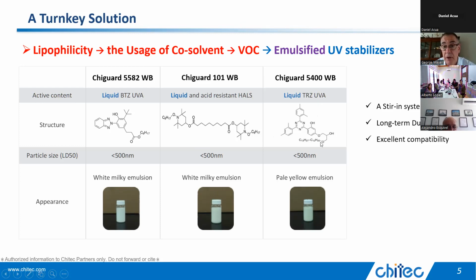The other UV absorber is a triazine. It's ChiGuard 5400. It's really the same molecule as our ChiGuard 5400 without the WB, just emulsified in a concentrate. The same molecule that Ciba-Geigy used to sell as Tinuvin 400. It's an extremely permanent material. Some of it reacts into your film or grafts in with this hydroxyl. It's a big molecule, so there's minimum migration. The only bad thing about the 5400 is its UV spectrum is not as broad. So if you need to protect out around 370 nanometers, it doesn't give you quite as much protection.